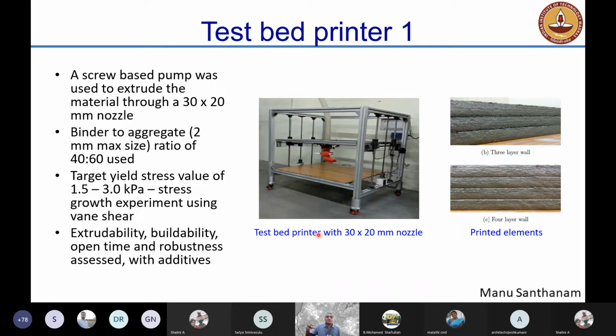At the same time, the material should be less viscous enough to extrude out of the nozzle. So those are characteristics that are quite different from what we are used to as far as self-compacting concrete is concerned. Okay, so here our initial mix design used a binder to aggregate ratio of 40 to 60. You can imagine that's a very large amount of cementitious material in it. And now, of course, we are optimizing this mixture to be able to print with even 25 to 75 binder to aggregate ratio, which is more or less similar to what you have in conventional concrete.